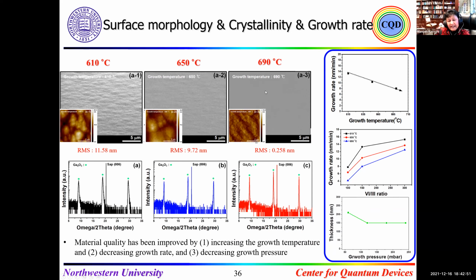We looked at the SEM and AFM, and as you can see, for 690 and 650 we got very nice X-ray results, exactly at 690, with a growth rate of approximately 10 to 15 nanometers per minute.